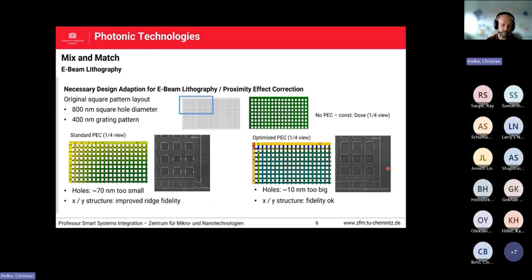The structure we characterized here was the hole array, which consists of 800 nanometer square holes with a 400 nanometer grating pattern in between. In electron beam lithography, it's very important to check the proximity effect correction, which is caused by the forward and back scattering of the electrons during the exposure of the resist and the material below. So you always have to define a certain PEC, based on the resist and the material you use, and you have different simulation methods to optimize your E-beam process itself.